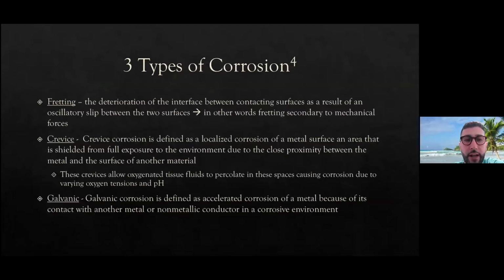The first is fretting, which is basically a mechanical corrosion, and that occurs due to oscillatory slip between 2 surfaces. There's crevice corrosion, which is exactly what it sounds like. It occurs at crevice sites. And so basically, when you have an area that's shielded from full exposure to the environment due to close proximity between 2 metal surfaces, so for example, a rod that's linked into a screw, the crevices allow oxygenated fluids to percolate, and it causes corrosion due to varying oxygen tensions and pH levels.